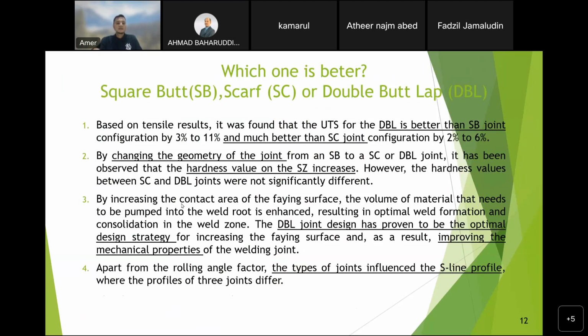By increasing the contact area of the faying surface, the volume of material that needs to be pumped into the weld root is enhanced, resulting in optimal weld formation and consolidation in the weld zone. The double butt lap joint design has proven to be an optimal design strategy for increasing the faying surface and, as a result, improving the mechanical properties of the joint. Apart from the rolling angle factor, the type of joint influences the S-line profile, where the profile for each joint differs.